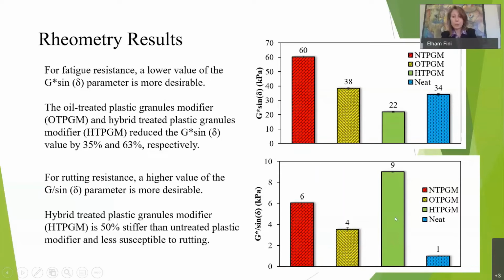Here you can see that the carbon one is way more than everything else. The oil treated is still better than the neat asphalt, which is what we use today on the roads. Because we added these plastics, the rutting resistance went up, as expected. But the hybrid treated was way up here and way down there. So that was sort of the best scenario in the fatigue resistance and the best scenario in the rutting resistance, which was impressive. So here we got 50% more stiffness and resistance to rutting compared to the untreated sample.